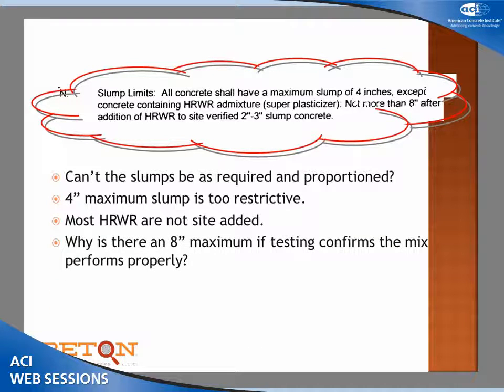And why have an 8-inch maximum slump when we know that we can make a 25-inch spread on the ground that has an RCP at 90 days of 100 coulombs passed? It's fantastic material. What's the compressive strength? I don't know. I don't measure it either, because it wasn't a design criterion for me. Who knows what workability is best?